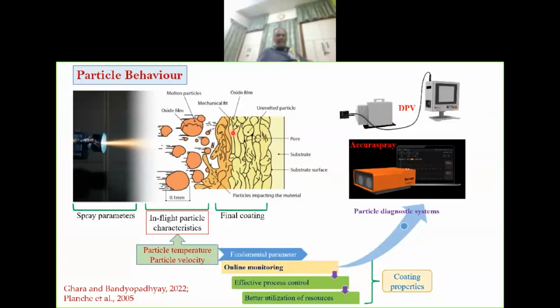Temperature too low, we have an unmelted particle. Okay. Or we get pores, or we get particle bounce back. If you have very high velocity, splats will badly deform. So these two are important. So once we can measure the particle velocity and temperature before impact, we really do not care what parameters brought this. It has given us these two derived quantities.